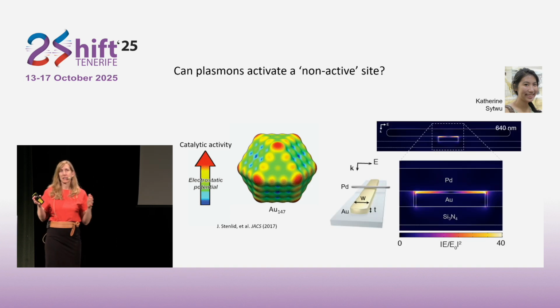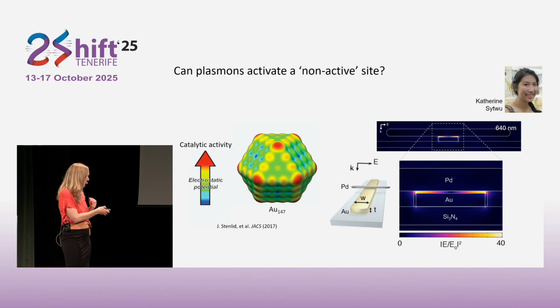So we set up a kind of a toy experiment where we had a gold nanobar and then a palladium nanorod on top. And this was a nice experiment because even though we have roughly nanometer scale imaging spatial resolution, we could still resolve the difference between the tips and the middle of the rod with very high accuracy to determine where the hydrogen was nucleating, and then propagating in the particle.